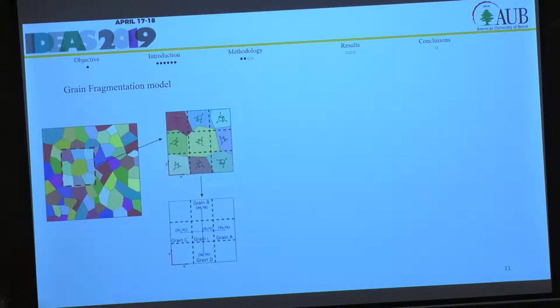So to go into the details of our grain fragmentation model, some assumptions are taken. First of all, we assume that each grain in the polycrystal, this schematic represents the polycrystal, and each color represents a different orientation for the crystal. So each grain is assumed to have a square shape, and each grain is assigned a position, orientation, and grain size, and it has 4 neighboring grains that will affect its deformation.